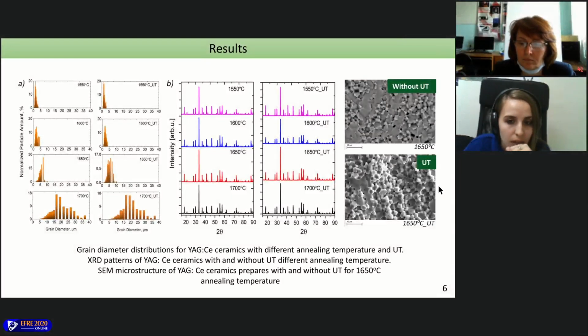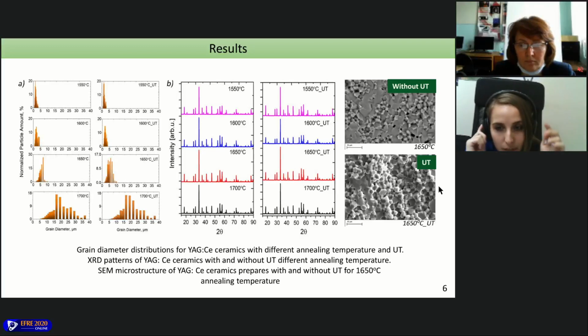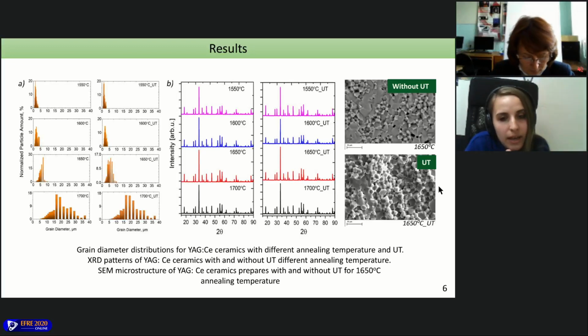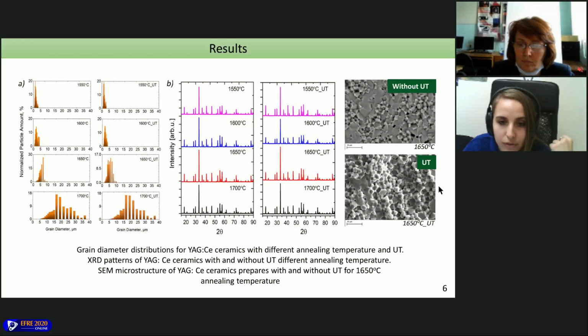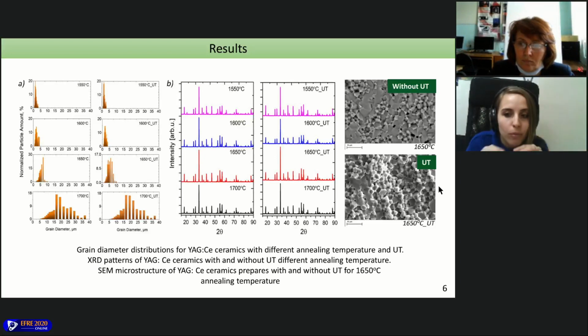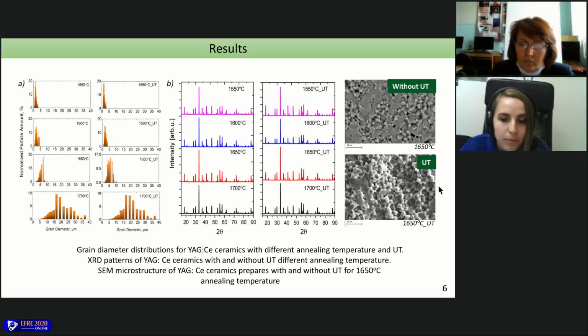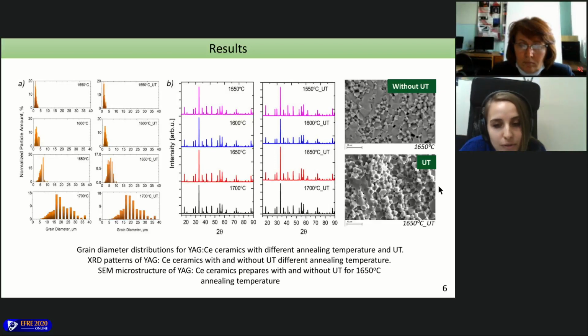So about results. First of all, X-ray phase analysis confirmed that ceramic samples have the stoichiometry of yttrium aluminum garnet with cubic structure, and we can see that the values of grain diameter in the left pictures increased from 0 to 5 micrometers and to 35 micrometers. And the sintered ceramics have a large number of pores, and the grain size remains at the level of several micrometers, corresponding to the average particle size of the original powder.